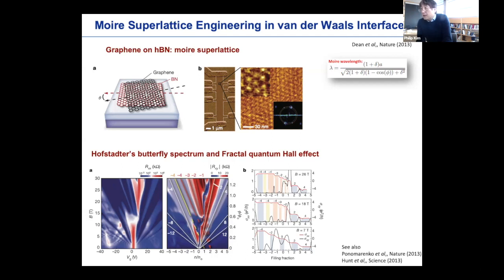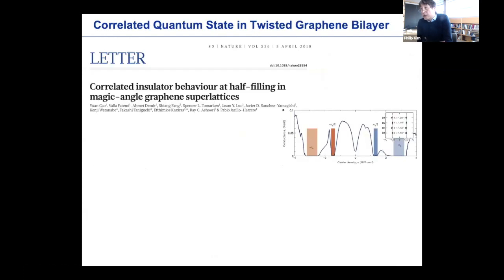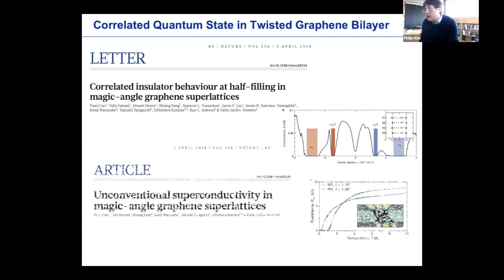Now, of course, the field really got excited 2 years ago when Pablo's group at MIT showed that right at the magic angle that Alan predicted 8 years ago, there are indeed some correlated insulating behaviors stemming from the very flat band formation, what theory precisely expected. Even more so, quite unexpectedly, when you dope this flat band system and move away slightly from this correlated insulating regime, the sample becomes a superconductor, and that's quite unexpected, and therefore very exciting new efforts started. I would say that within 2.5 years of time passed now, the field is really expanding rapidly.